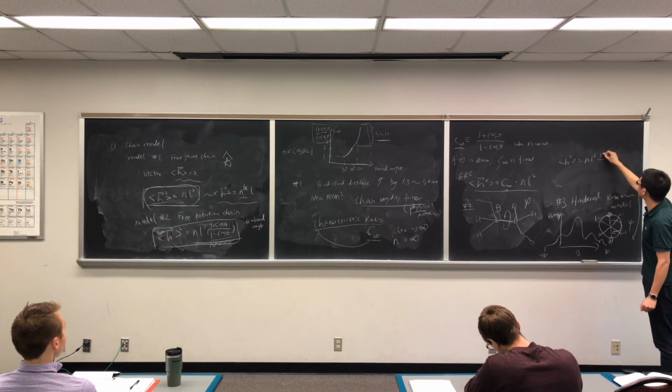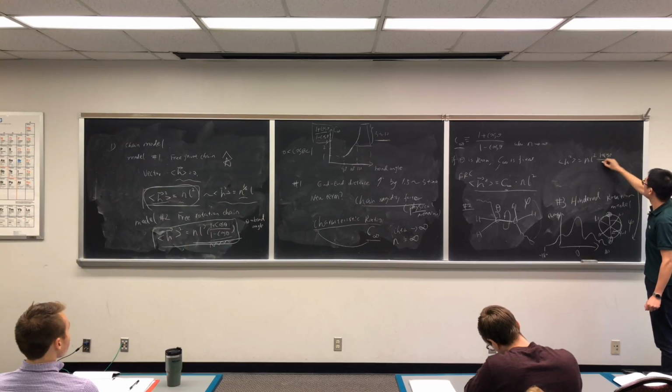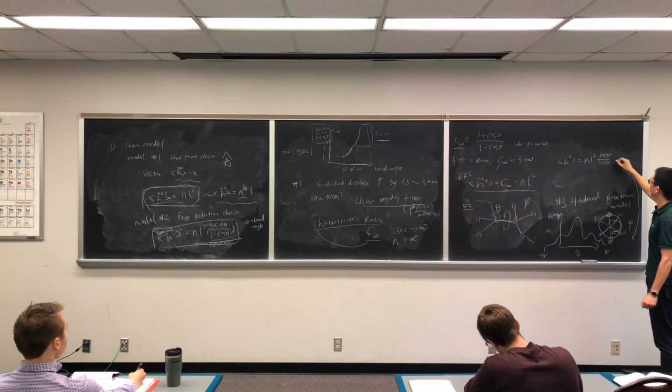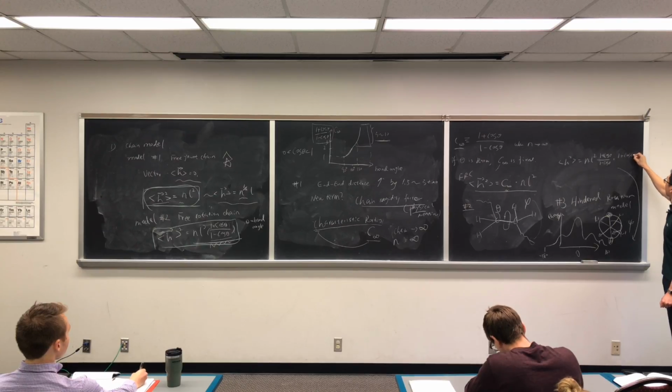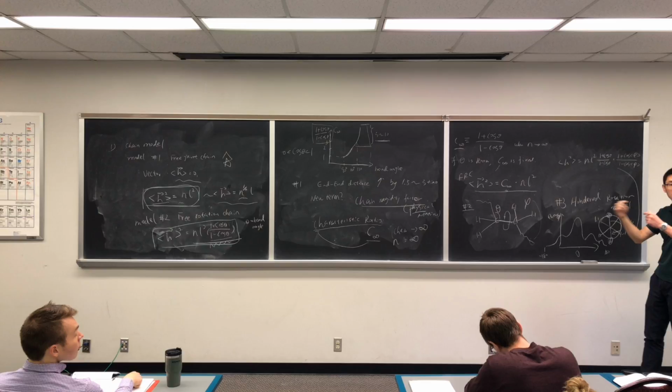So you're still going to have 1 plus cosine theta over 1 minus cosine theta. And it will multiply one more term: 1 plus cosine phi average over 1 minus cosine phi average. Because you think about the energy rotation potential, phi will be a new term.